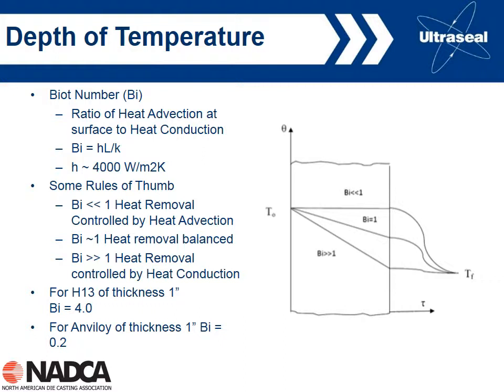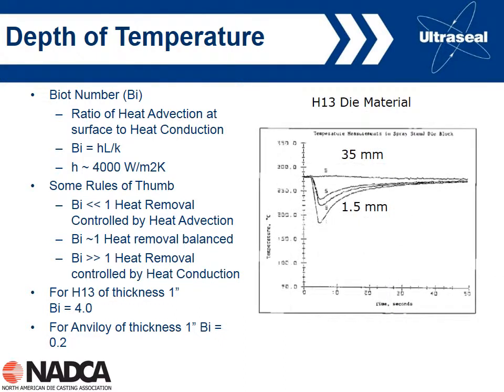If we think about a much higher thermal conductivity material such as Anviloy, which people use in parts of their die, the Biot number is 0.2 for a 1-inch thickness of Anviloy, so that's much less than 1, and so we get this kind of gradient with Anviloy. So what does this mean in terms of heat extraction?